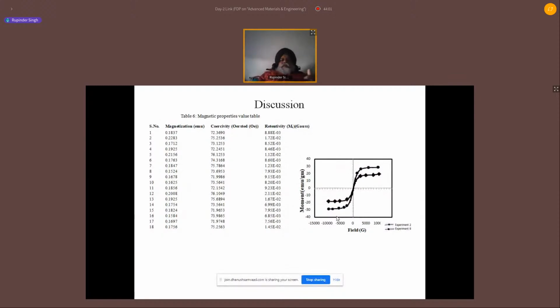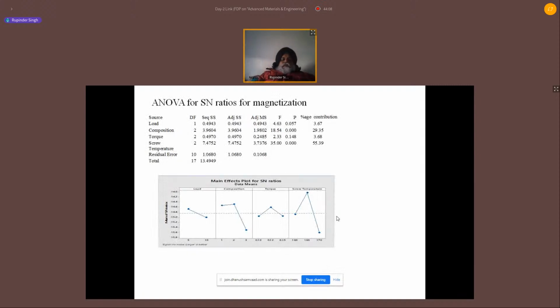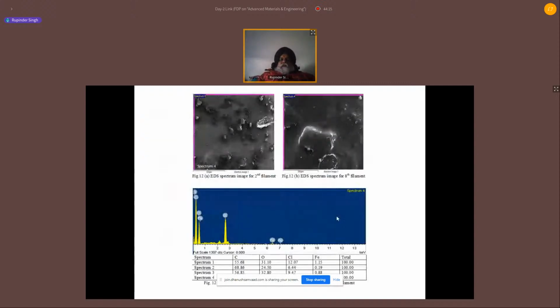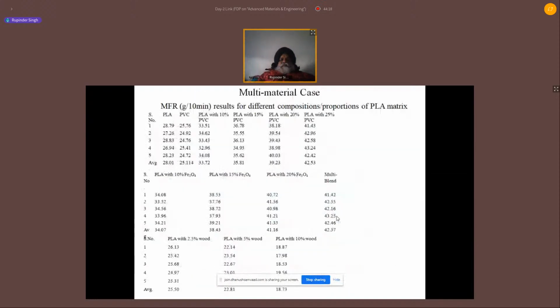So these types of basic observations we did for the selected composition of the material, and then we did some ANOVA analysis, a typical statistical tool, to understand which parameter contributes more to a particular property. Then some SEM and EDS analysis was done. You see from here, I have PLA, so repeated experimentations were performed for finding their melt flow index. Then for PVC, then with the different reinforcement of PLA into PVC, like 10%, 15%, 20%, 25%. So what will be the effect of the two types of reinforcement? Then what will be the effect of the multi blend on the melt flow index of the material? Similarly, for the reinforcement of Fe3O4, and similarly with the reinforcement of wood, we see what the effect is.